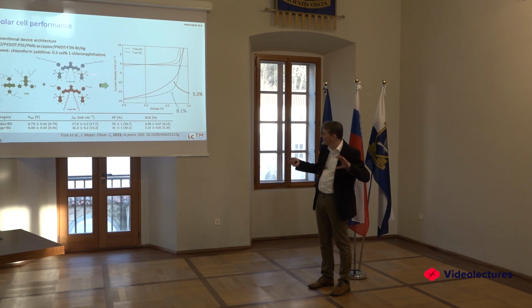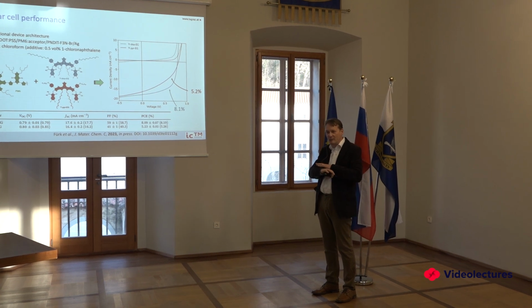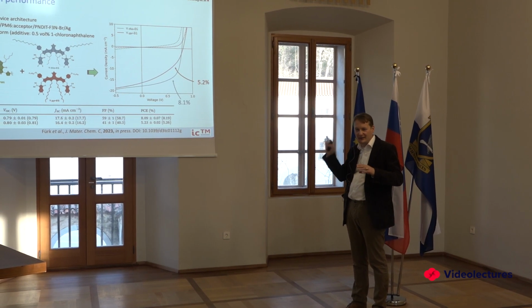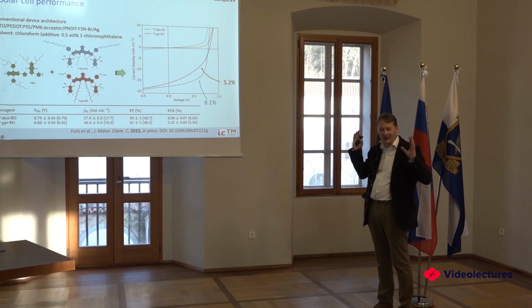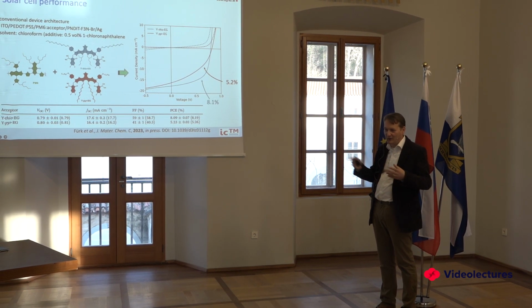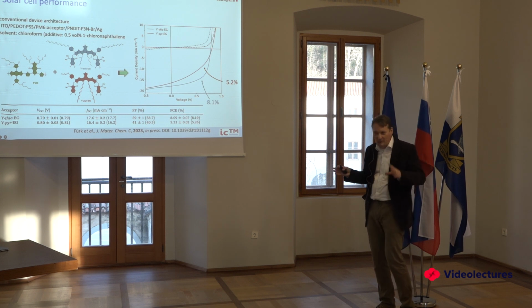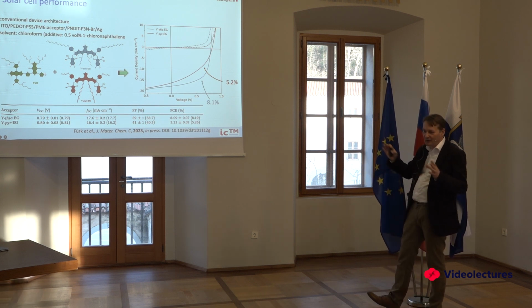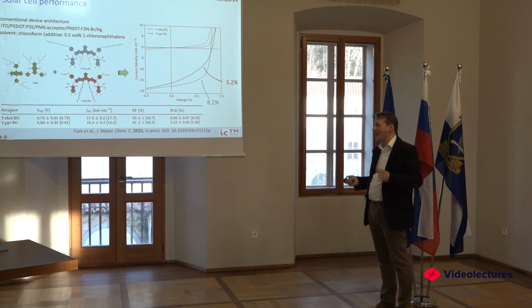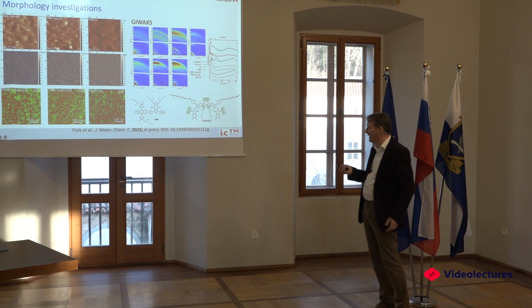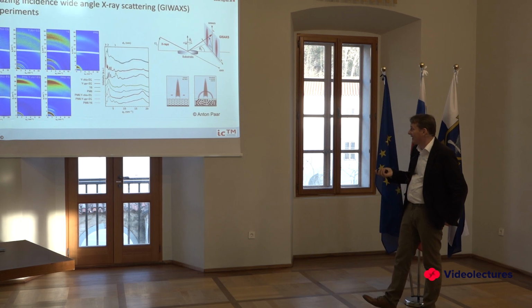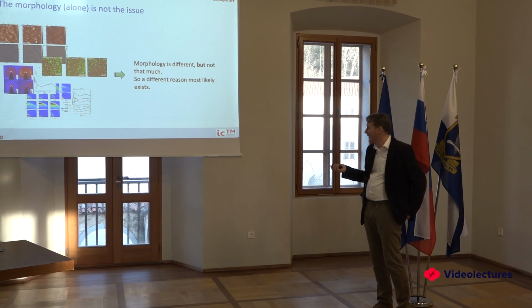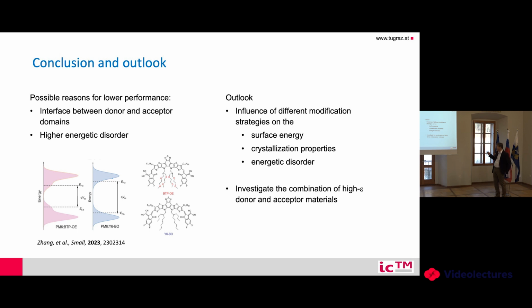So actually, these glycol chains here are not connected to the electronic structure of the material. So you have the same optical spectra. They have the same UV-vis absorption, you have the same CV, so it's the same electronic properties. So it's really only the side chain. They are not connected to the electronic system. So this is very strange, and we thought it was very strange. And at the same time, we already speculated that it might have something to do with the electronic disorder, which people were also thinking about.